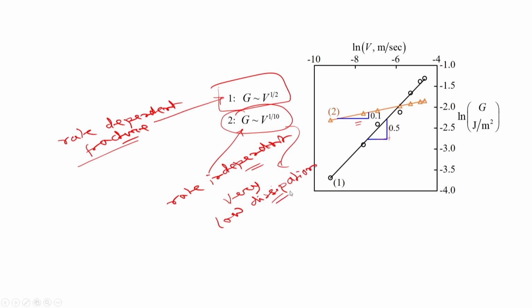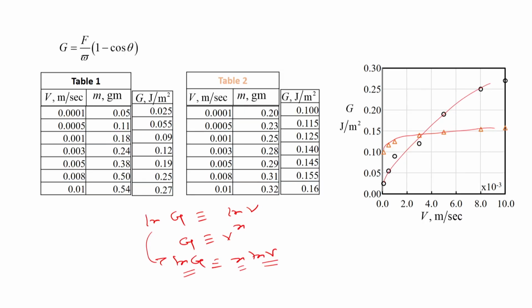So, what it also means is that the kind of G value that we get here, for example we can find an average, that G can be equated to work of adhesion, and that is very close to the thermodynamic work of adhesion, because irreversibility has not led to any amplification over here. So, these are the various things that we can say.